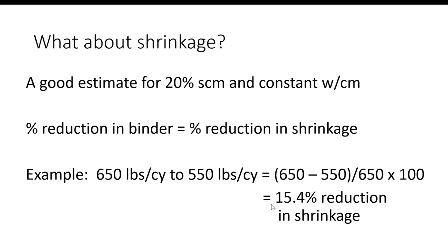So how about shrinkage? People love to ask me this question. Does this reduce shrinkage? Does the tarantula curve reduce shrinkage? Only if you reduce paste. The paste is what shrinks. If you don't reduce paste, you will not reduce shrinkage.